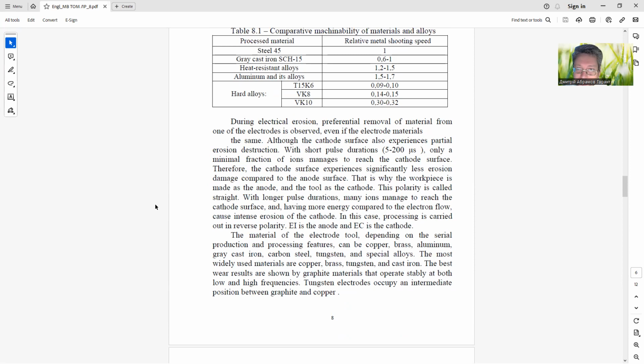During electrical erosion, preferential removal of material from one of the electrodes is observed, even if the electrode materials are the same. Also, the cathode surface experiences partial erosion destruction with short pulse durations from 5 to 200 microseconds. Only a minimal fraction of ions manages to reach the cathode surface. Therefore, the cathode surface experiences significantly less erosion damage compared to the anode surface. That is why the workpiece is made as the anode and the tool as the cathode. This polarity is called straight.